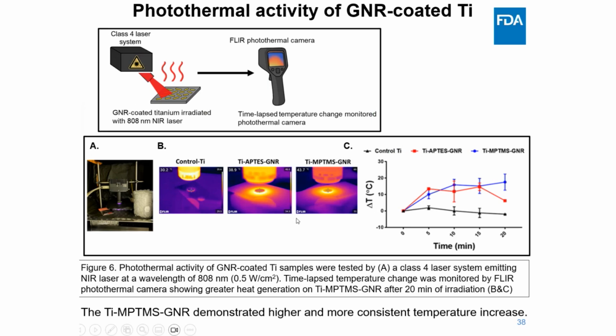Next, we wanted to test whether these gold-coated titanium surfaces could generate heat when exposed to light, a property known as photothermal activity. So here in this figure, we expose each sample to an 808 nanometer near infrared, or NIR, laser for 20 minutes and used a thermal camera to monitor the temperature change over time.